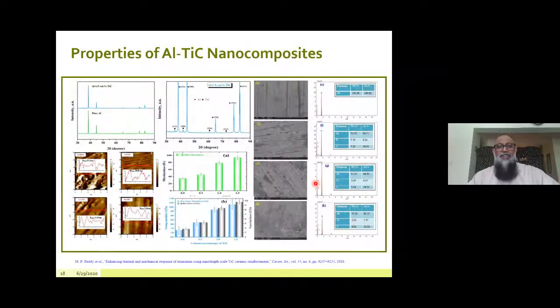So the final composition is aluminum titanium carbide nanocomposites, and a similar trend was observed. Let me explain the AFM results. The surface hardness increases with the increase in TiC nanocarbide content in this matrix because of the presence of TiC particles in the matrix. The hardness increases with the increase in TiC composition in the aluminum matrix.